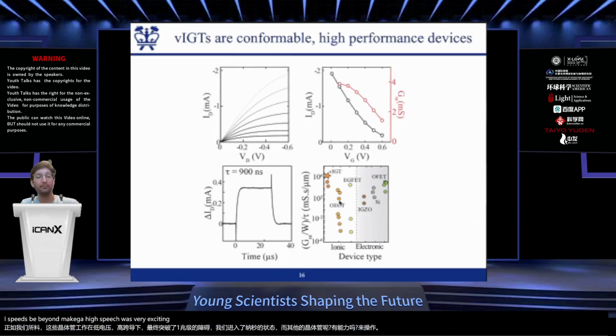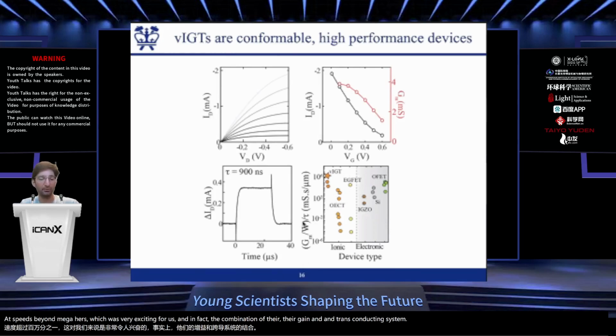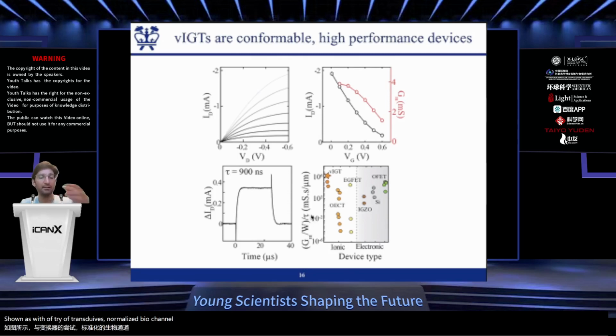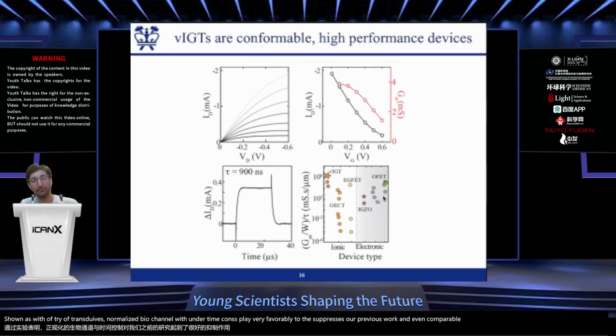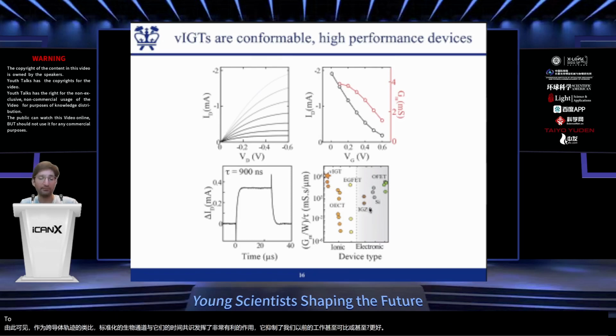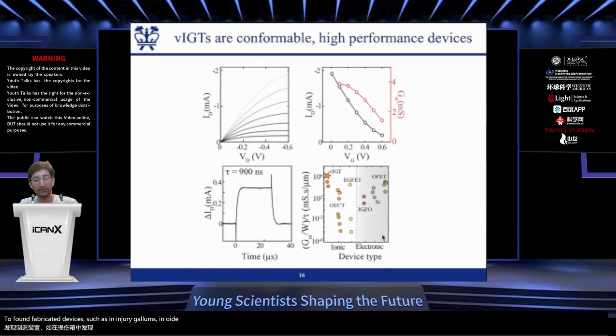And in fact, the combination of their gain and transconductance, shown here as transconductance normalized by channel width, and their time constants plays very favorably. It surpasses our previous work and is even comparable or even better than foundry-fabricated devices such as indium gallium zinc oxide or even silicon technologies. Of course, those are flexible foundry made.